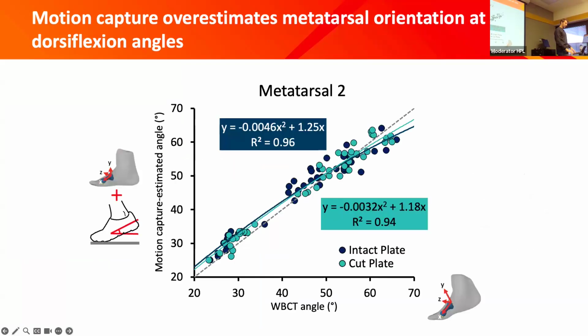So from this, we came up with some data that we could use to potentially correct that metatarsal orientation. So on the y-axis here, we have our motion capture estimated angle. And then our x-axis here, we had our directly measured angle of the metatarsals from that weight bearing CT. Each of these is a different data point from each one of those scans of all the participants. And we can essentially come up with these two curves that we can use to correct the data. One curve is for the cut plate, one curve is for the intact plate condition. So yeah, that's kind of what we use to correct that data there.